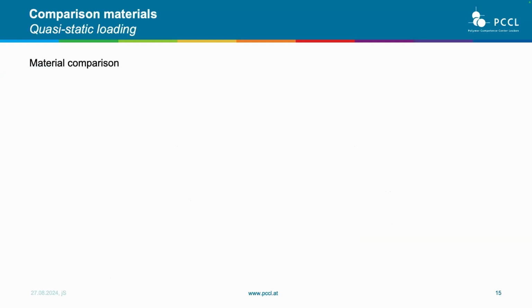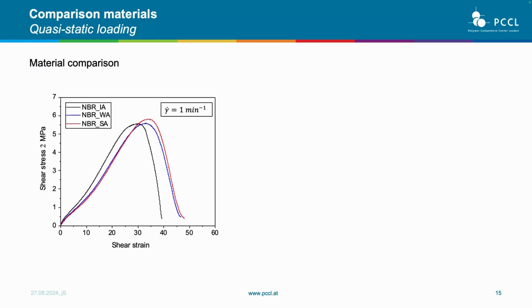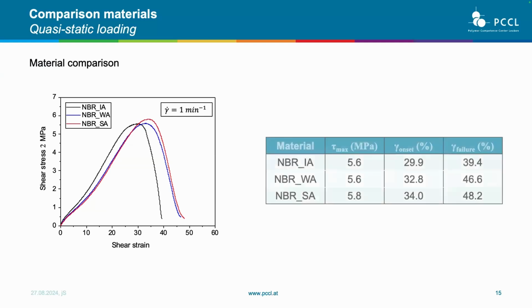So that's what we did. We then checked different materials, with the different adhesives used. And these are the quasi-static tests. We see that the curves are pretty similar, and also the data sets are quite similar, even though we can observe some difference already between the industrial one and the other two.